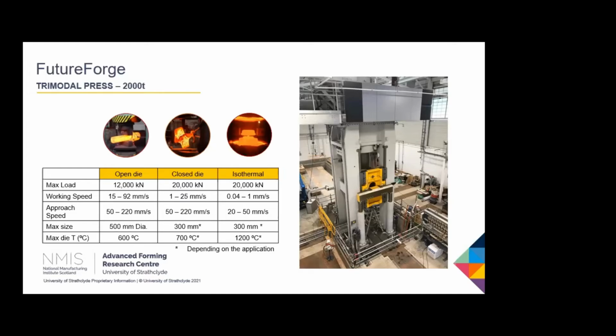Deliberately, we didn't make the cross-sectional area too large. We didn't want to compete industrially. We didn't want to be doing industrial or commercial activities. So the maximum diameter of billet that we can take is only 0.5 metre in diameter, but it's constrained to be only 1,000 kilograms. So to do the calculations, we're starting off with a very short steel billet. For closed die, we can only do a maximum component diameter in the order of 300 millimetres for both isothermal and closed die. So from a disc perspective, it's too small. So we're not going to be commercially engaged.